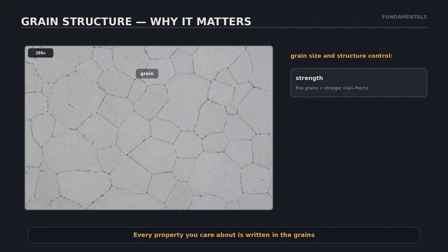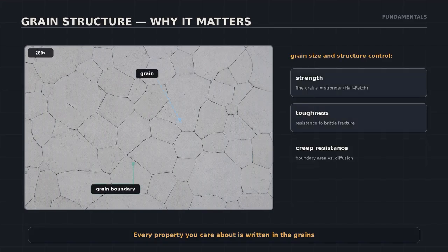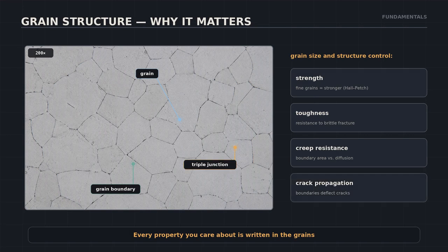Grain structure isn't academic, it controls everything. Fine grains mean higher strength, through the Hall-Petch relationship. Grain size affects toughness, and therefore resistance to brittle fracture. Boundaries govern creep resistance, they're where diffusion happens. And boundaries deflect cracks, so they shape how cracks propagate. Read the grains, and you read the material's future.